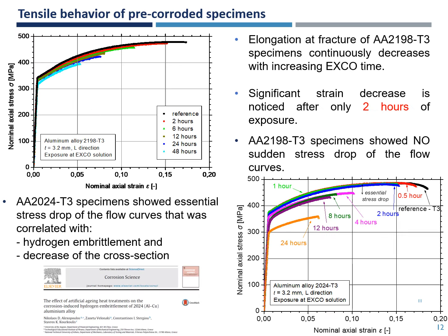Moving on to the experimental results and analysis. Regarding the tensile behavior of pre-corroded specimens, a previous work of the authors showed an essential stress drop of the flow curves of aluminum alloy 2024 in T3 condition after only 4 hours of corrosion exposure, shown with the magenta color in the right figure.